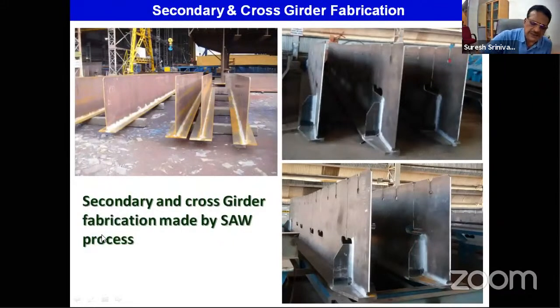And all these secondary girders and cross girders were completely done in semi-automatic welding with a fixture which was designed at site and applied at site. So we had to do a lot of fixturing design, assembly, and then using it for actual fabrication. Now this secondary girder to the flange are all full penetration double bevel fillet T-joints. So after welding one side, you had to back gouge, regrind and weld it again with semi-automatic welding.